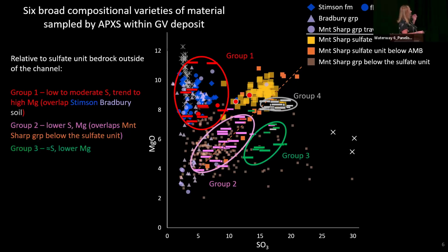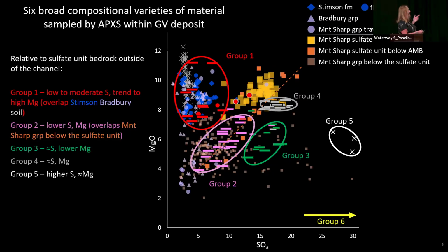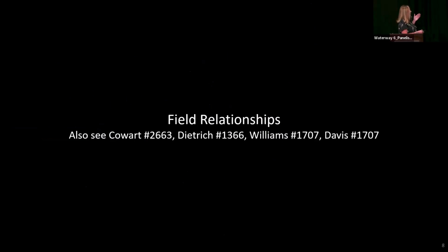And again, group 4 is close to the bedrock outside the channel, but trending to higher sulfur and somewhat lower magnesium. And then we've got our group 5 again with that high sulfur, which again is not showing high magnesium. So the magnesium and the calcium are not elevated, associated with that high sulfur, and none of the other cations are either. And then finally, again, group 6 plots off here. I'm going to skip over that slide.